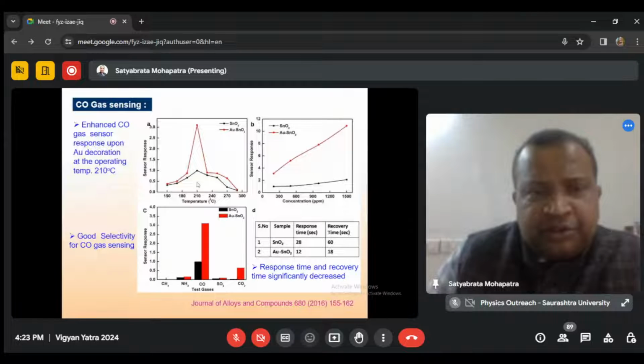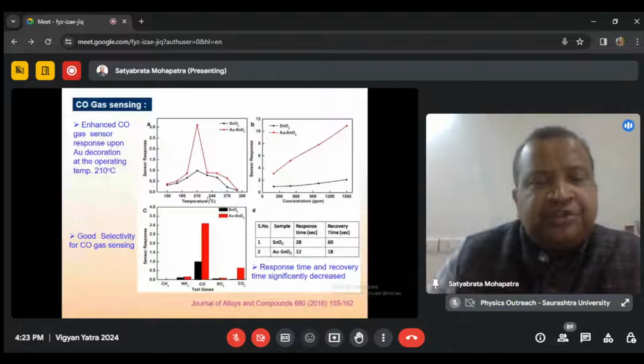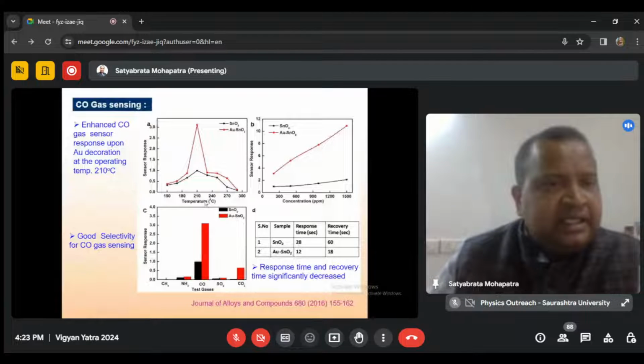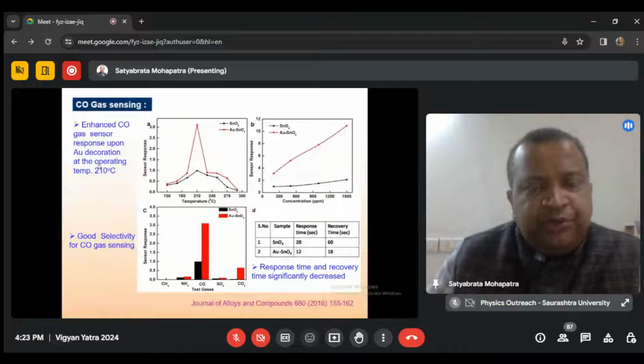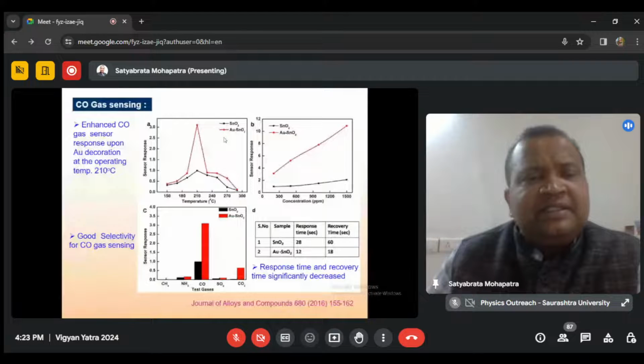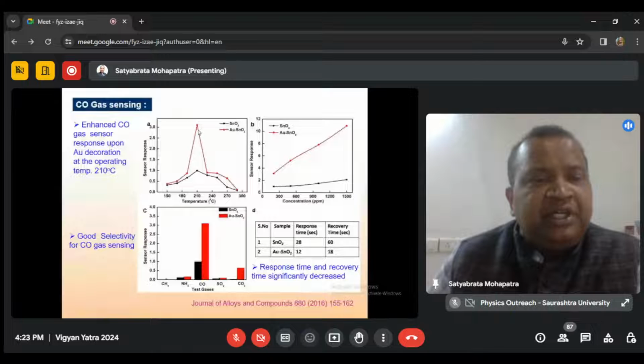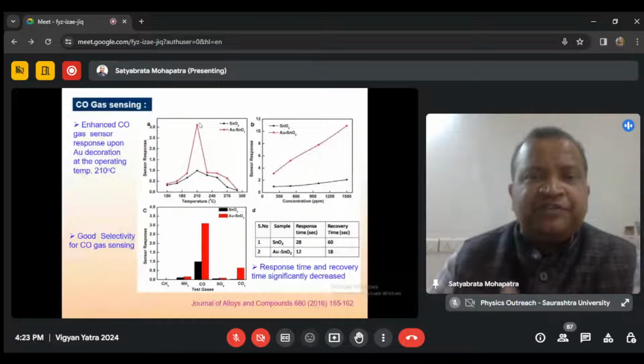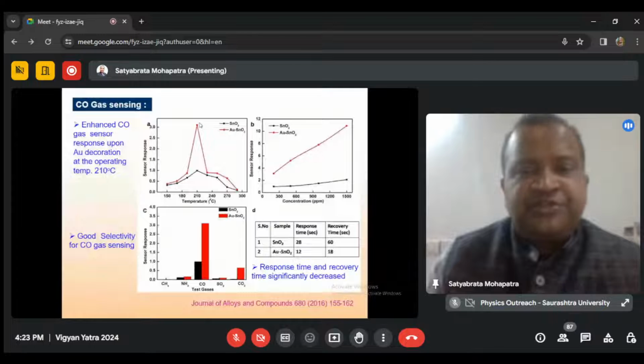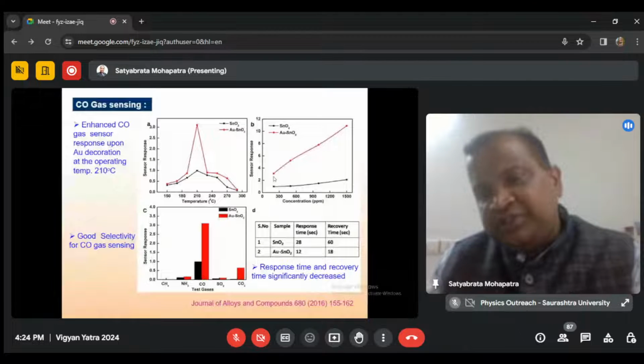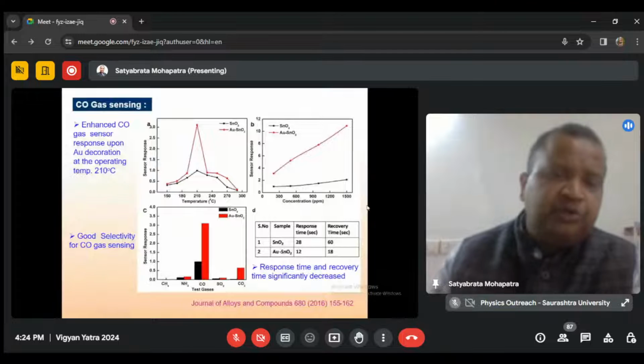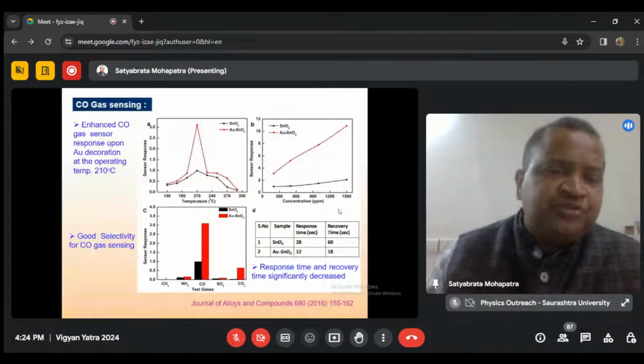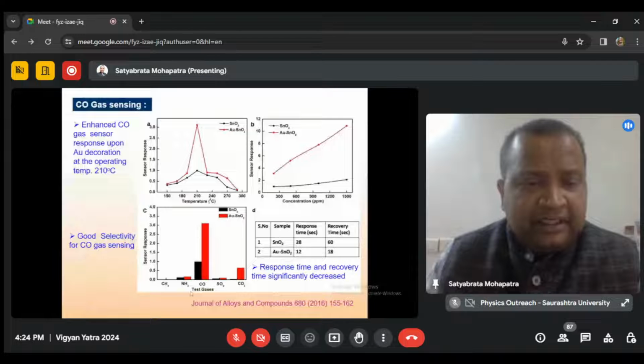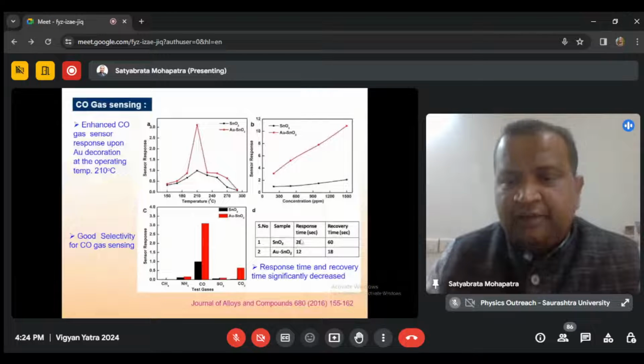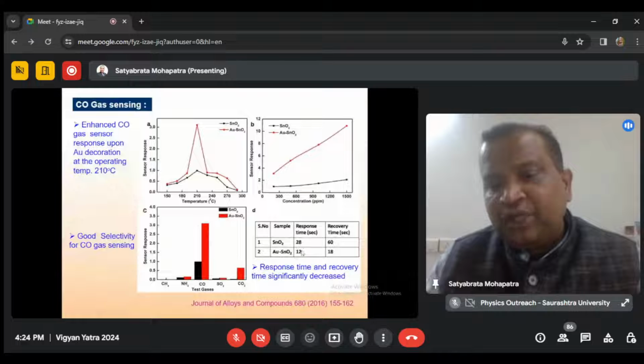Now we can see that the operating temperature is reduced to 210 degrees centigrade, and if you decorate them with gold particles, there is a clean, threefold enhancement in the sensor response. So the first thing is that there is a strong enhancement in the sensor response. Of course, the response increases with concentration, but we want to focus on a relatively low concentration of carbon monoxide gas. And you can see that the response time reduces from 28 seconds to 12 seconds just by depositing a nanoparticle thin film.